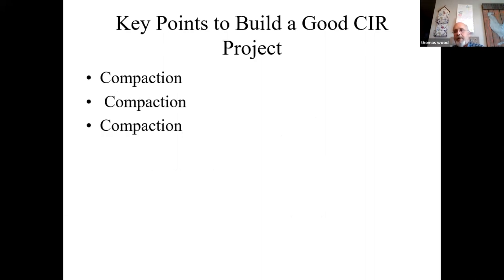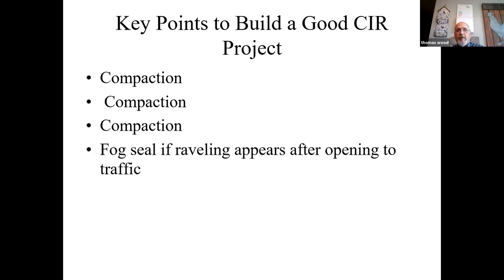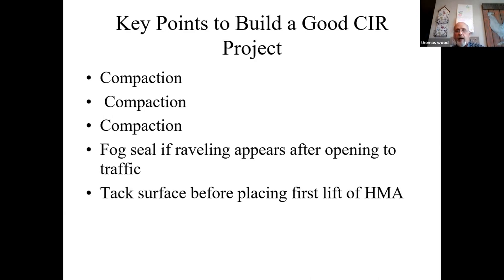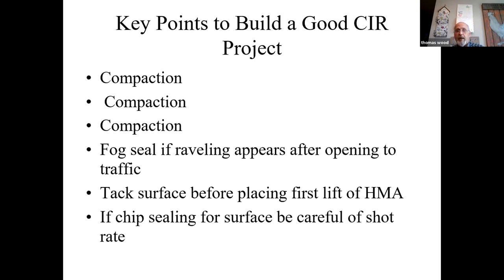Compaction. If I've seen issues with in-place recycling, it's lack of good compactive effort. And then I'm a strong believer, after you've done the CIR and it's been open to traffic for a day or two, if you're not going to pave it right away, or even if you are going to pave it, fog seal it. It helps prevent raveling, and it also acts like a tack for when we put the hot mix on it. And for sure, tack it before the first lift of HMA there.